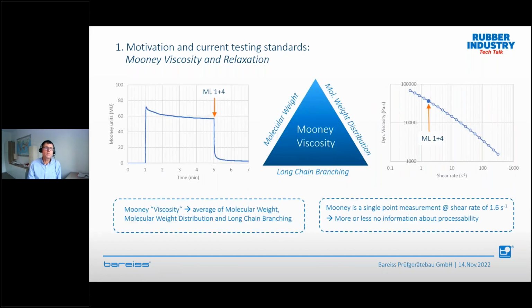But finally, what we are using from this test, and that is what you see on the left graph, we are using this ML1+4 value. It's a 1-point measurement. So Mr. Mooney decided that 8.31 Newton meter are 100 Mooney units, and we call it Mooney viscosity. Again, it's only a torque. If you transfer this Mooney value onto the right side on the real viscosity curve as a function of shear rate, that is what you see here, then it's only one data point of a whole viscosity curve.